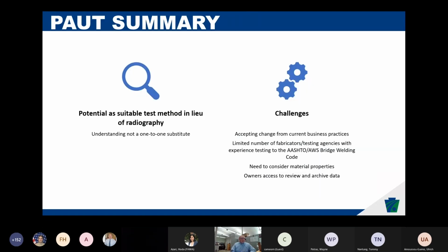So ultimately, there's good potential to use phased array in lieu of radiography. There has to be some understanding, though, that they're 2 different processes. Radiography is good for some indications, and ultrasonic testing is good for others. So they're never going to be truly a one-to-one comparison, as was shown in that last example, where we were actually finding flaws with ultrasound that were not picked up with radiography.